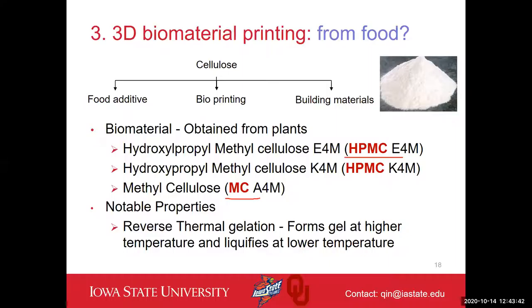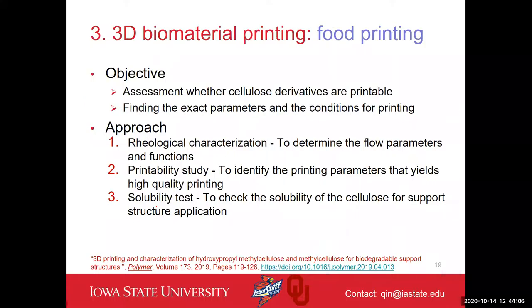There are some interesting properties of this material. It has the so-called reverse thermal gelation, so it forms gel at higher temperature and then liquefies at lower temperature. They are also water soluble, which means that with more water, the material becomes very soft and easy to remove. That was the initial motivation. So we started to evaluate how different cellulose materials can be printed or not, and how to define their printability.